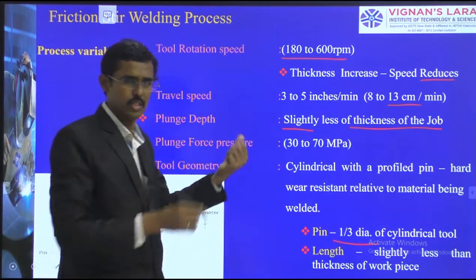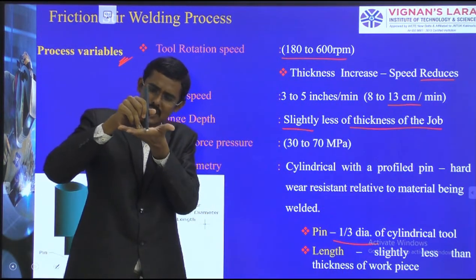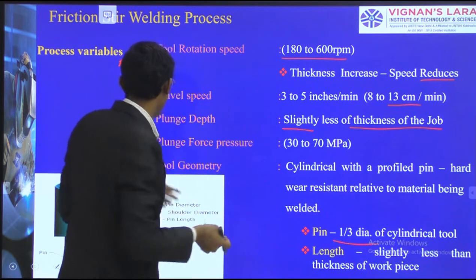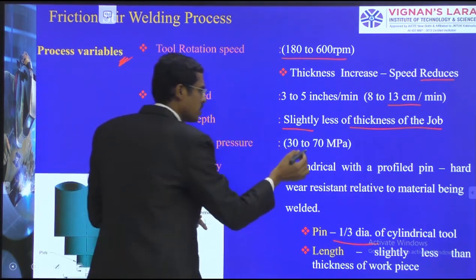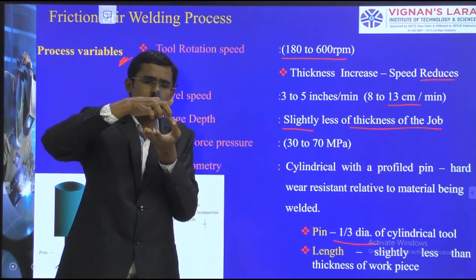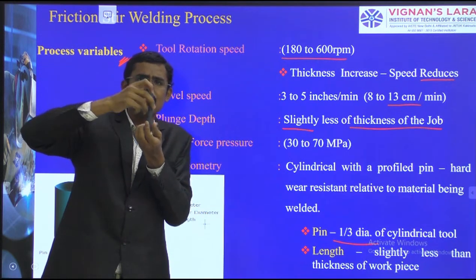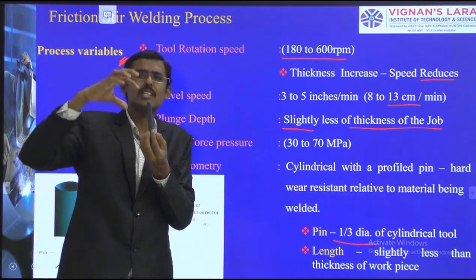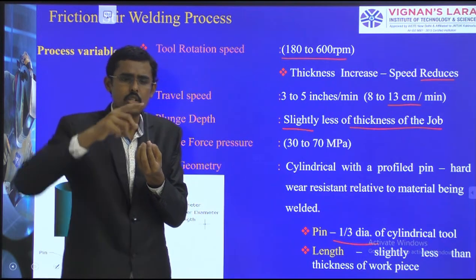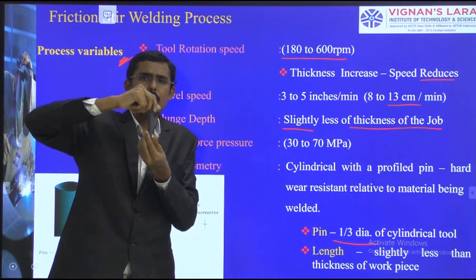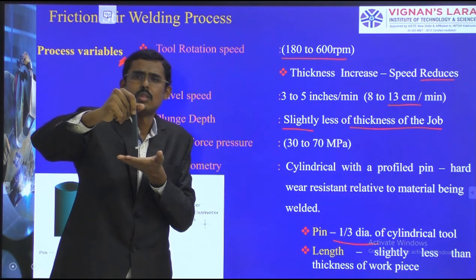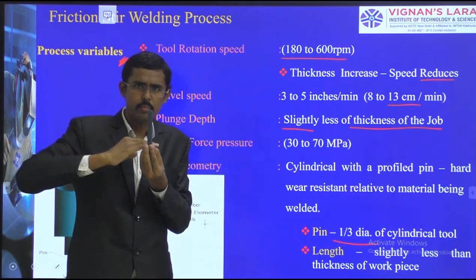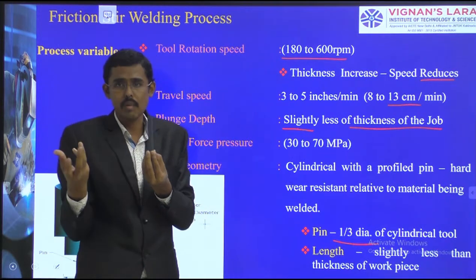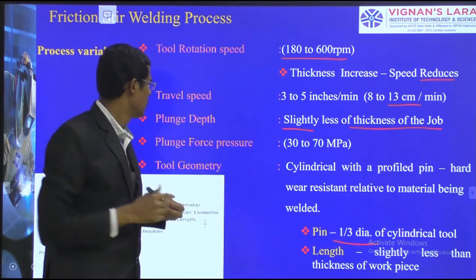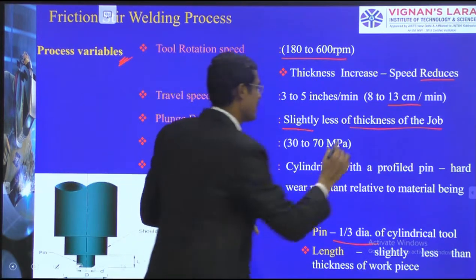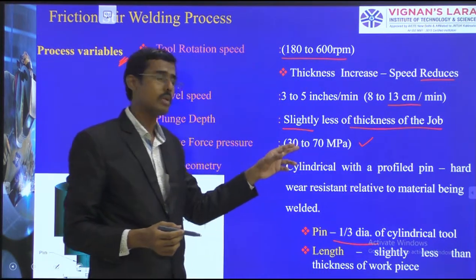In the video also we have seen the specimen went directly to this location and it has moved the thickness of the specimen. Plunging force, it should be held. Plunging, this tool is to be held here, otherwise it comes out. After drilling it will be like a drilling action there. So it is to be tightened well and it should be rotated and then it should move. The shoulder should stop the scrap chips from coming out. Therefore we should give pressure there. That is approximately 30 to 70 megapascal for aluminum we are giving.